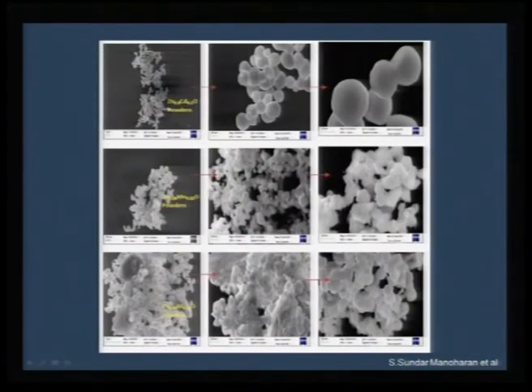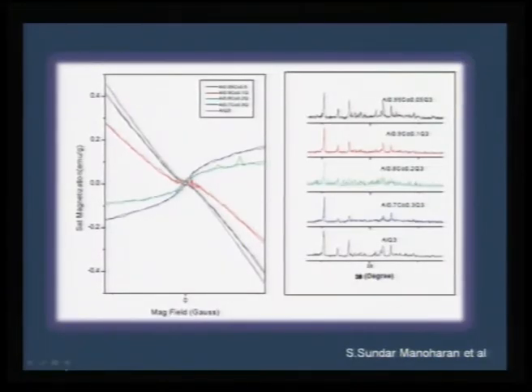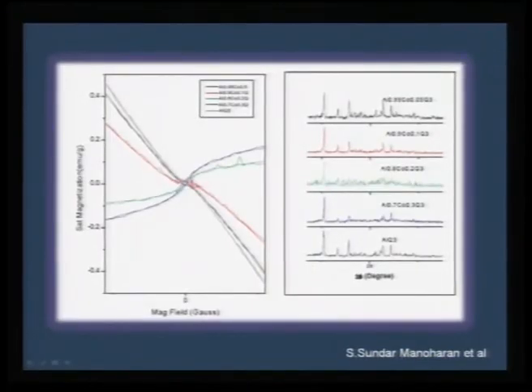And we can also prepare similarly cadmium based compounds or manganese based compounds or nickel based compounds. As you would see here, even with less than 10% of doping, the crystal morphology or the surface morphology of these oxides change in a variety of ways. Last two slides, I would like to sum up that we can also try to tune the magnetism by using the same solid solution precursor notion by substituting very little amount of cobalt from 0% up to 30%. And as you would see here very clearly, the precursors are showing the same morphology even up to 30% of cobalt doping, but the precursors clearly show a very different trend as far as the magnetic behavior is concerned.